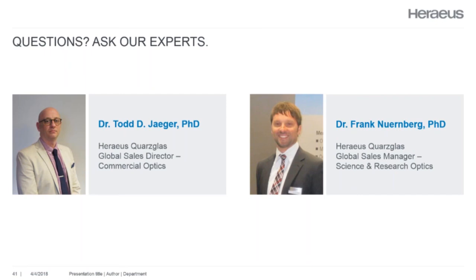Additional annealing processes enable us to reduce the stress in the material, which, for example, comes after the raw material production, during the mechanical treatment of the material. This increases stress as well, and during an additional annealing process afterwards, we are reducing exactly this stress, and what we can see as well is that the optical homogeneity is reduced. However, the optical homogeneity in the material is more guided by the chemical composition and the distribution of the chemical impurities in the material, and the stress-induced birefringence is more influenced by the geometry itself, sharp edges, and mechanical treatment outside. So there is a small correlation possible, but not 100%.